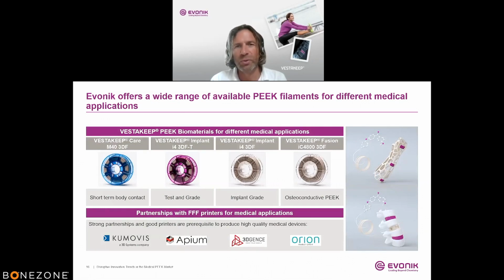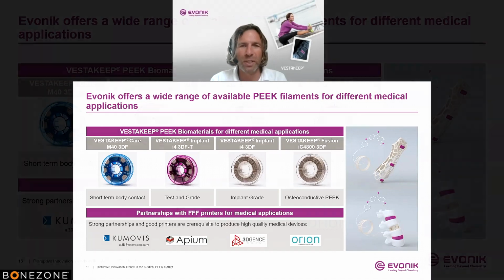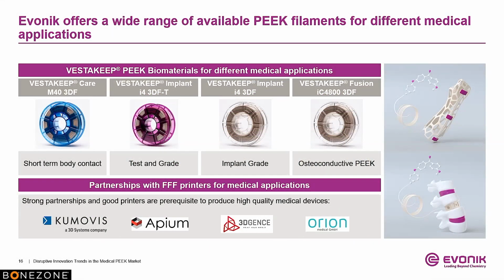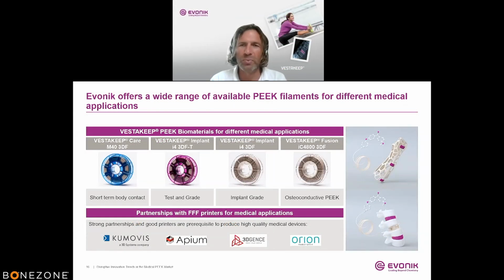Now going from injection molding to 3D printing, we started there with four different filaments. One for short-term contact, one as a testing grade, then the long-term implant filament, and our latest filament development is the VestaKeep Fusion IC 4800 3DF, and this is also because of the good results of the injection molded samples. We also expected to have this effect of osteoconductivity also on the printed surface. That's why we developed that filament and then did some tests on it.